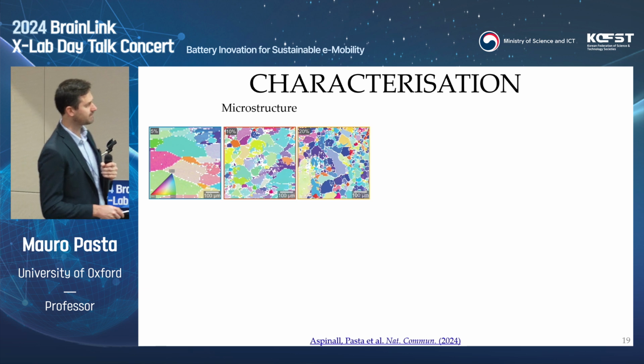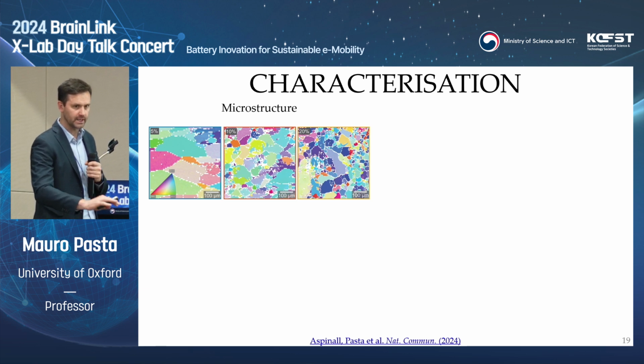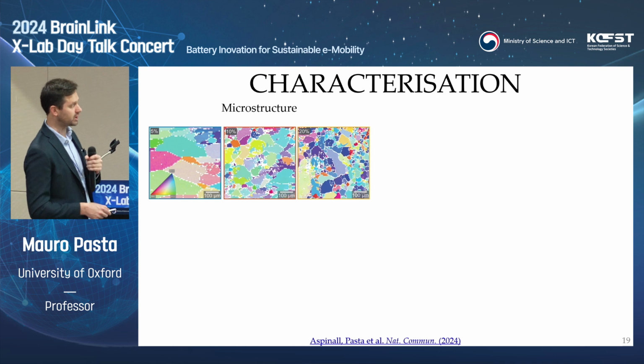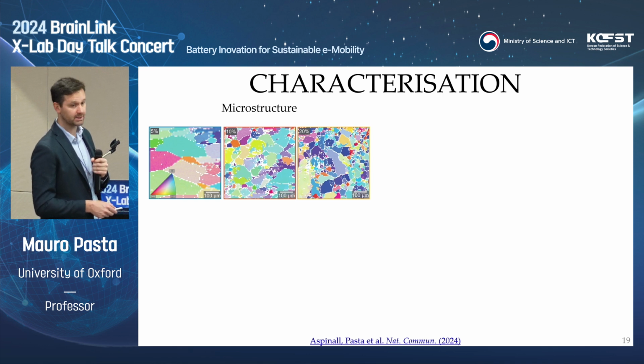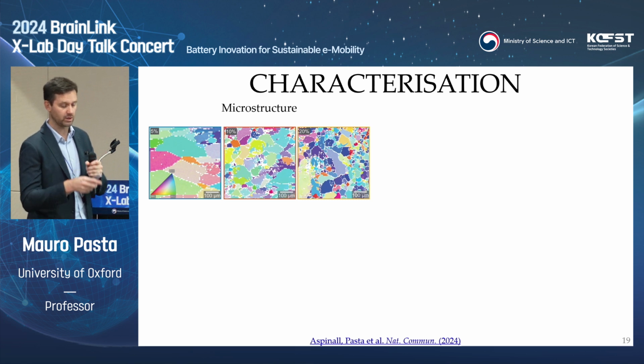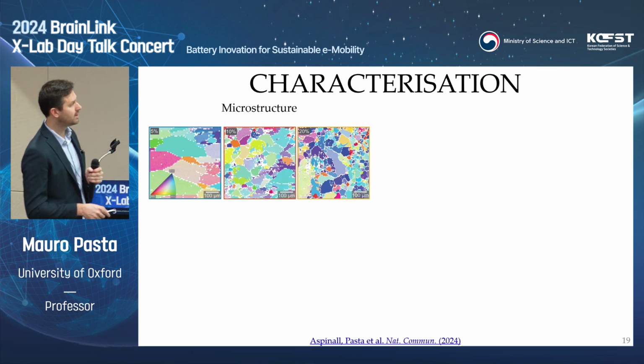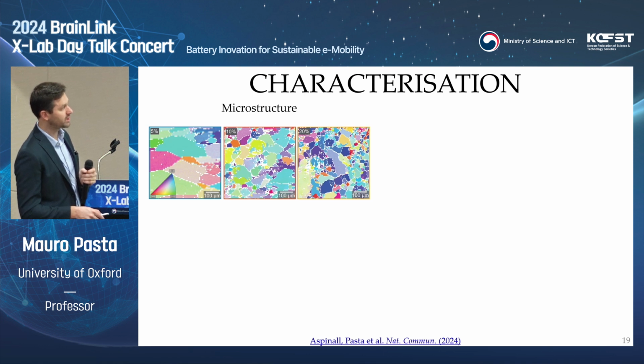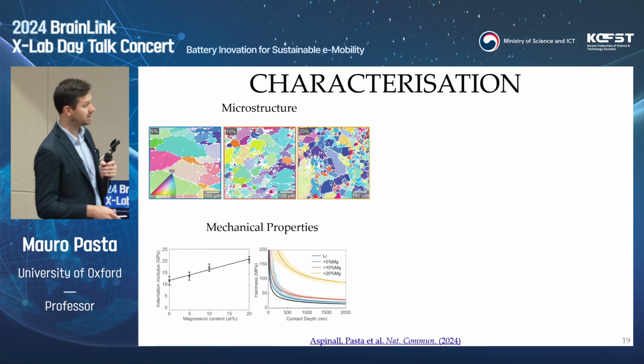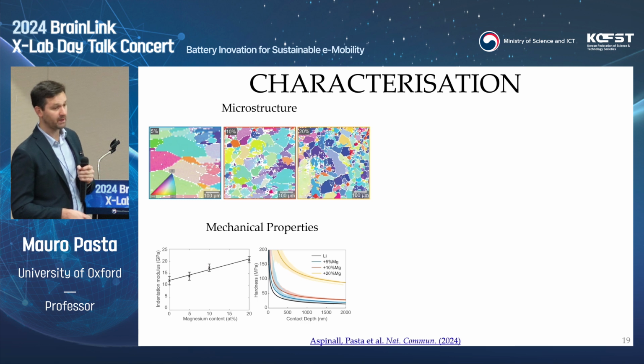So you can microtome, so polish the surface of your lithium metal foil, and then characterize it using EBSD, for example, electron backscatter diffraction, that allows you to basically tell what these grains are and what their crystallographic orientation is. So all these different colors correspond to a different crystallographic orientation of your crystal here. You can see that as you increase magnesium content, you are affecting a bit the crystallite size, but they're still quite big. They're in the order of microns or millimeters in the case of lithium because of the very, very high diffusivity. We can then test the mechanical properties by indentation as a function of the crystallographic orientation.